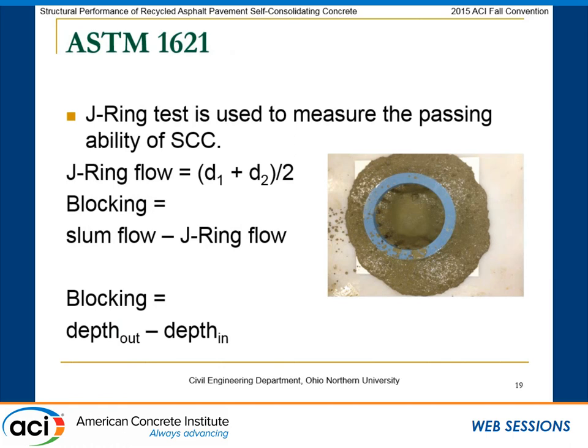The J-ring test measures the blocking from the reinforcement. You use the J-ring, look at the spread of the concrete, and measure the diameter in two perpendicular directions, then take the average of the diameter. You can measure blocking by taking the difference between the slump flow results and the J-ring results. If you have a small value, then you don't have much blocking.